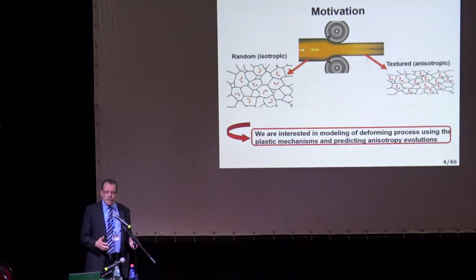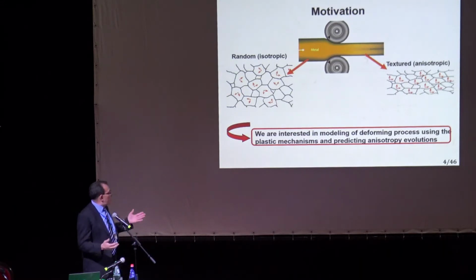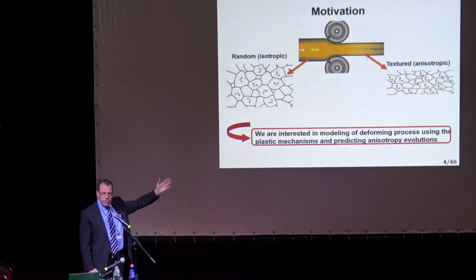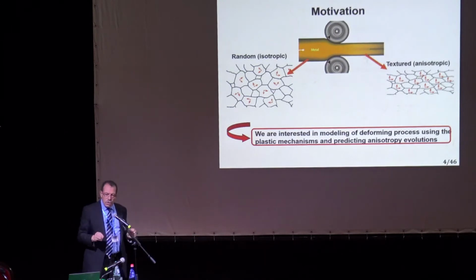So the motivation for crystal plasticity is the fact that when you have deformation processes like in metal forming, well, you may have initially an isotropic material, but at the end you will have anisotropy that is due to morphology change, the shape of the grains and their orientation, also some behavior that is due to grain boundaries, but mainly what I will focus on is the crystallographic orientation, okay? That we call texture or preferential orientations of crystals. So as is shown in this schematic here, you may have an initially random distribution of crystallographic orientations, but after a process like a rolling or forging or so, you will have highly oriented material, and you have different orientational components that we call texture components or preferential orientation components.